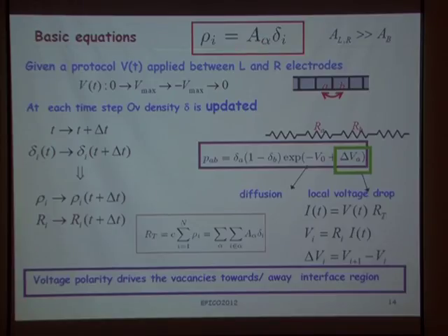In a way, we take into account in these A values all the geometric characteristics of the interfaces and the fact that we have high resistive interfaces compared to the bulk. So these A values are going to be larger at the interface compared to the bulk. Even so, if we want to characterize, for example, two different interfaces, we can take two different values for the left and right interface. This is something we can play with, and I'm going to show you how, as we change this relation between the A values, we can go through different behaviors in the IV characteristics.